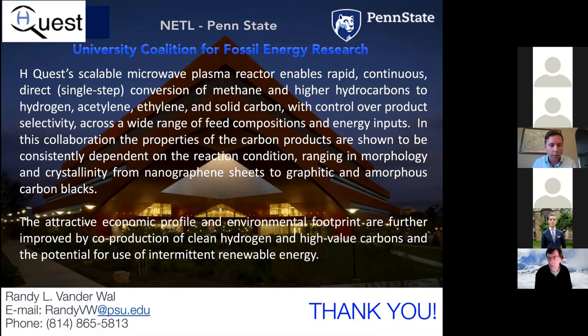Great. And one final one from me, having run microwave atmospheric reactors myself, I know one challenge is that the carbon buildup on the walls of the reactor will disrupt the process as it absorbs the microwave energy directly there rather than getting to the gas. And so do you have that problem? And if so, what's your injection strategy? So do you inject the methane through the microwave region itself, or do you inject it downstream in the effluent of the plasma?